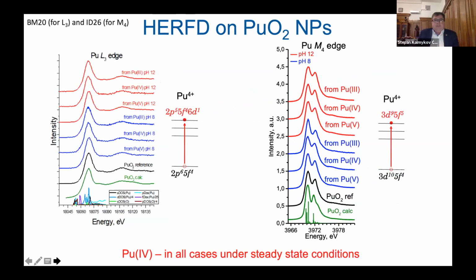So this is one of the examples. This is the characterization of the samples of plutonium nanoparticles. The interesting thing that we were asking is whether there are some traces of plutonium-3 or plutonium-5 or even plutonium-6 present in the structure of these nanoparticles, probably on the surface of these nanoparticles. So we use L3 HERFD, and you can see the spectra are quite similar. So there are no great spectral changes in this case. And we also have here the reference spectra of microcrystalline plutonium dioxide, and plutonium O2 calculated.